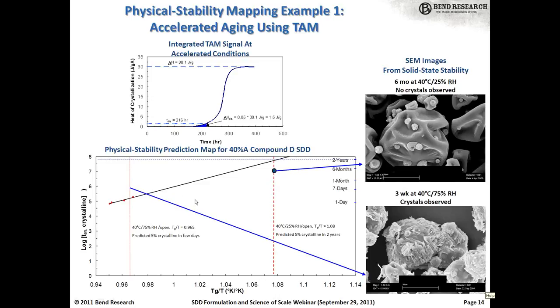What's done is you do this at a number of conditions, and you have to know the glass transition temperature through DSC or other measurements. And then you can plot that data as shown below here, where the y-axis is log of the time to crystallize, and the x-axis is Tg over T, which is effectively a measure of mobility. And you can plot out the data, which of course is taken at fairly aggressive conditions so that you observe crystallization, and extrapolate that out to less aggressive conditions. And you can predict what the kinetics of stability over time are at various conditions.